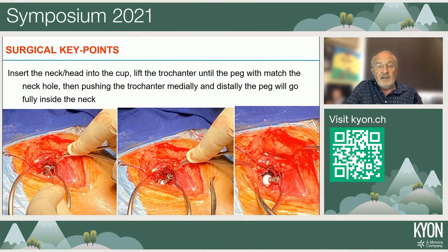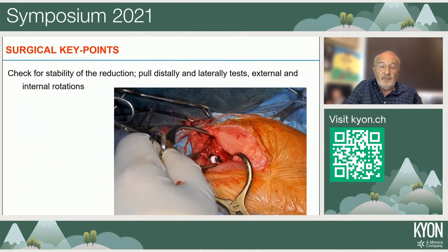Finally, as soon as the stem has been fixed with all the screws, we need to insert our head and neck. So we assemble them on the table, and then we put the head and neck inside the cup, and then we pull the trochanter until we can match the peg of the stem inside the hole in the neck. And then pulling again distally, we will be able to match completely to have the peg going fully inside the neck. That is a very simple maneuver that can be done even in larger dogs, but in small dogs it is very important because we have much less room to make our reduction.